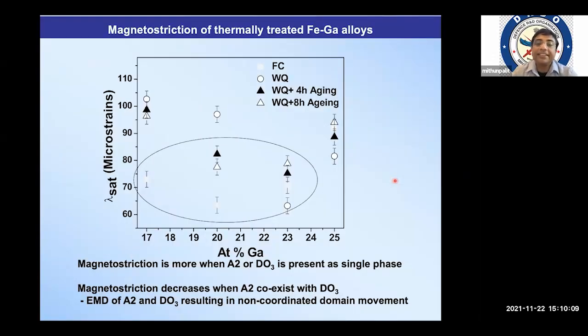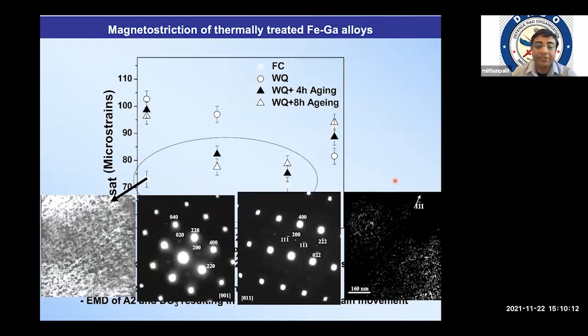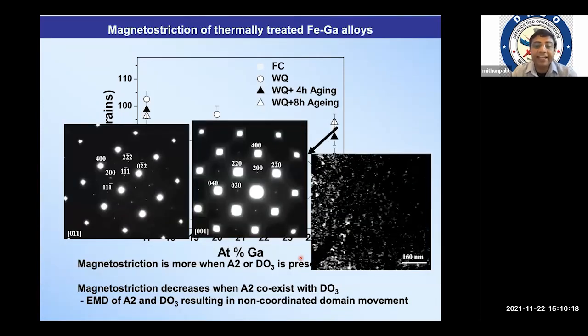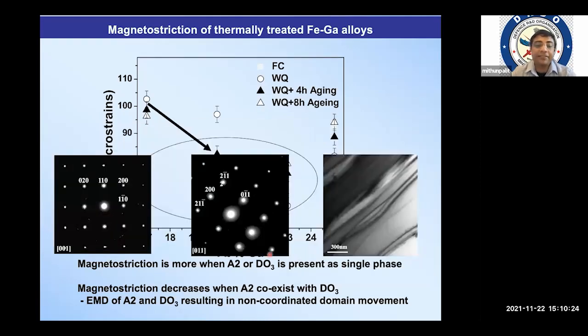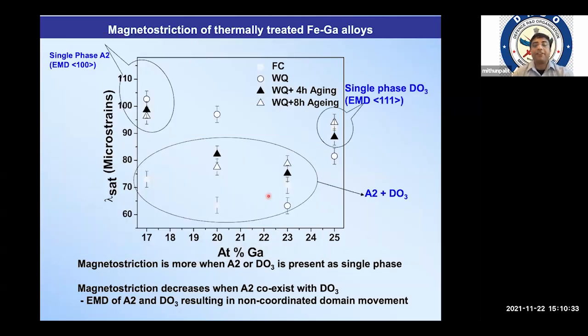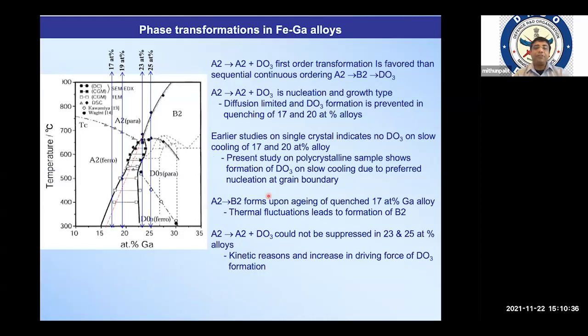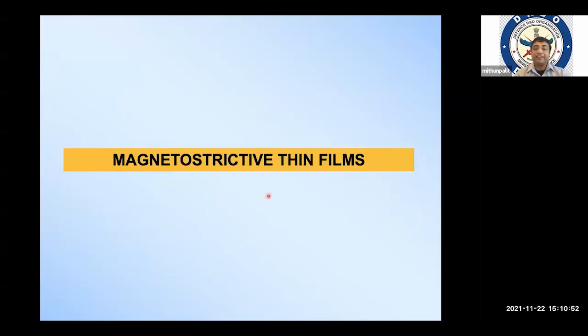We have also studied the reason for that using transmission electron microscopy. We can find certain ordered phases present in the slow cooled material. Basically, they are damaging to the magnetostrictive performance of the material, whereas in the quenched material, you don't find the superlattice spots corresponding to the ordered phase, and accordingly we have better magnetostrictive performance. And we also analyzed how this phase transformation occurred in this material, and accordingly developed a material with 400 ppm and a very steep slope of magnetostriction. I'll not go into the detail of this for this audience.